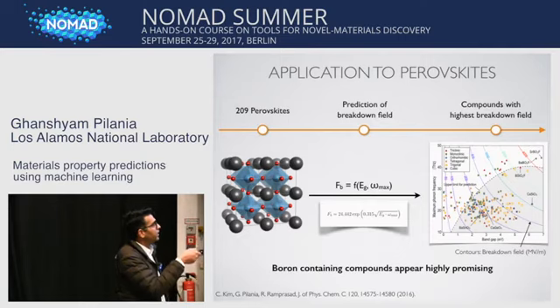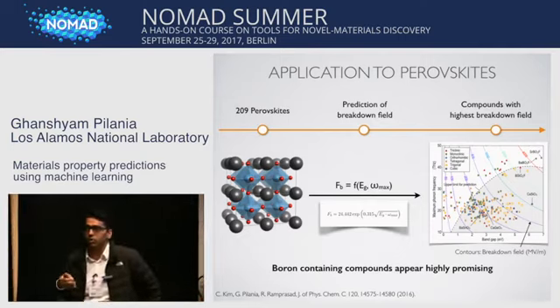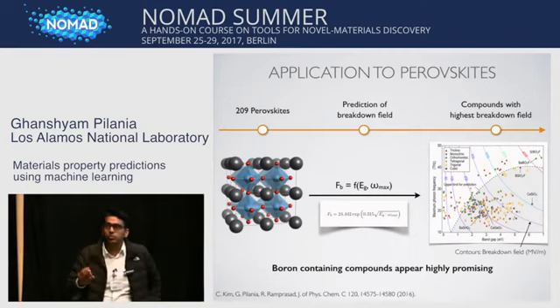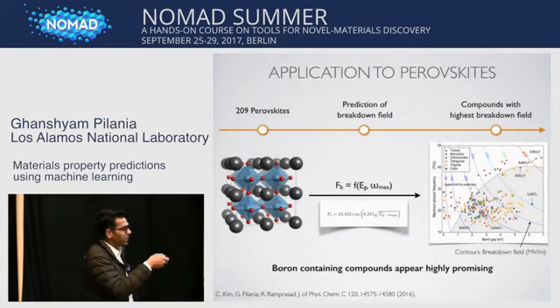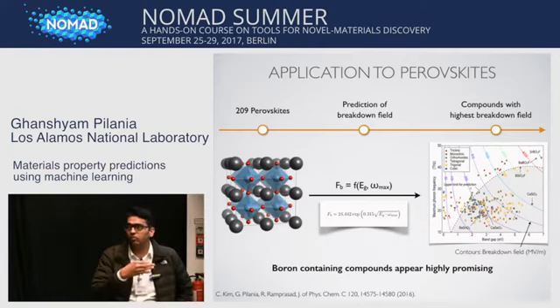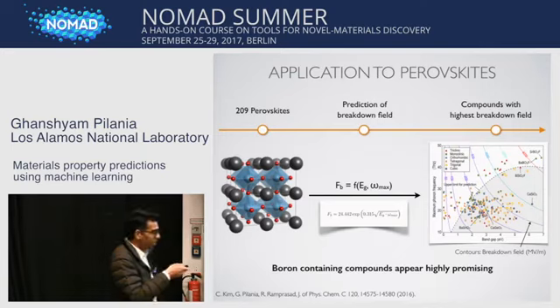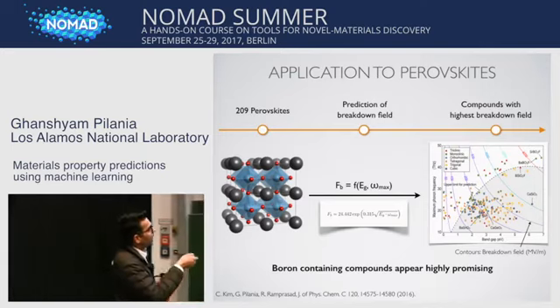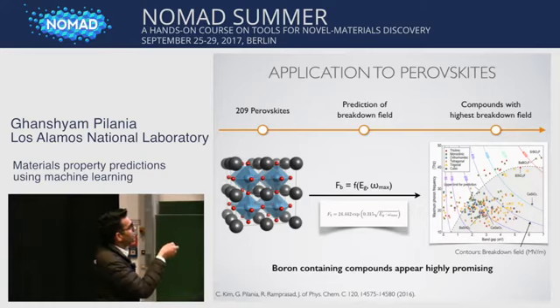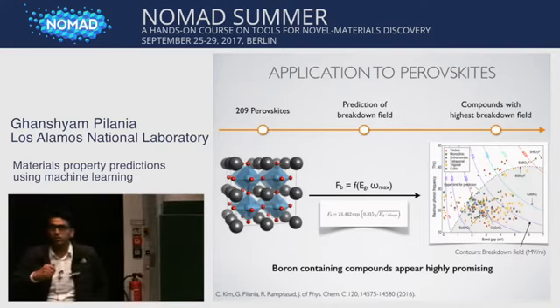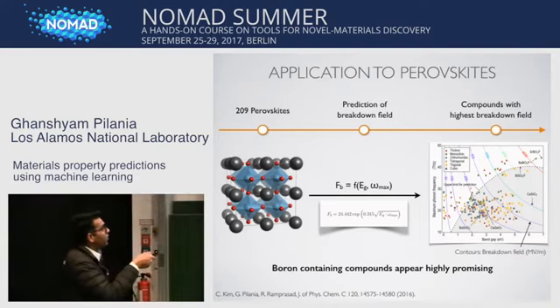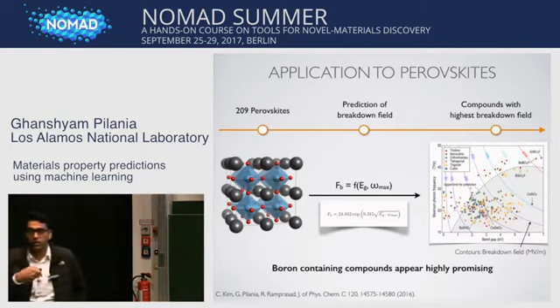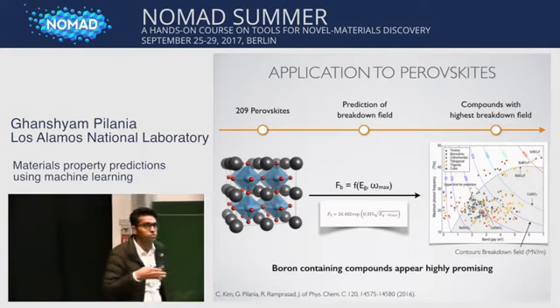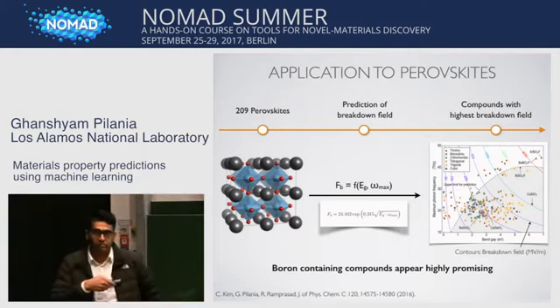The gray region below the dashed line is where we expect that machine learning model to work, and that means in our original 82 binary octets, most of the compounds that were in the training set had their band gap and phonon cutoff frequency falling in this range. So if we are going out of this gray area, we are really going out of the domain of the machine learning model. Now the interesting thing that comes out of this is that when we go higher in band gap and higher in phonon frequency, that's the region where our highest breakdown field strength compounds reside, and many of these compounds actually have boron in them. So it is interesting to note that boron containing compounds seem to show very high breakdown field strength, and we are currently looking into this in further detail.